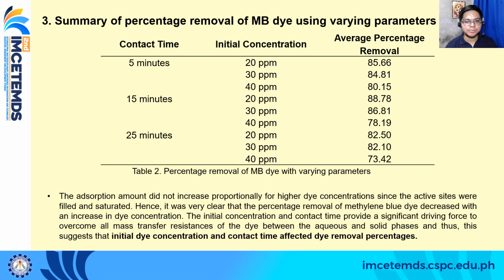Now, this table represents the summary of the percentage removal of methylene blue dye using varying parameters. As mentioned, we varied the initial dye concentration and the contact time. From the table, the best condition that we have is at 20 ppm initial concentration and 15 minutes of contact time, which has 88.78% of average percentage removal.